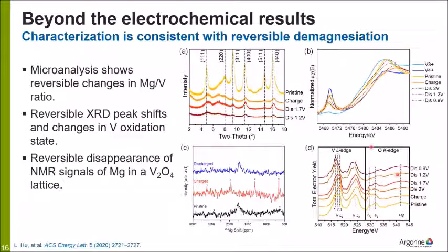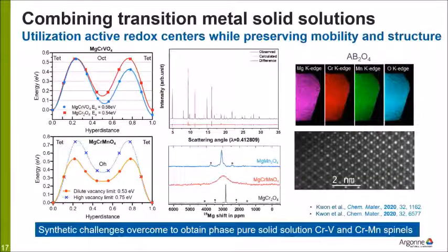And finally, we even looked at surface-specific versus bulk-specific emission spectroscopy results. And once again, you can see, even at the surface, this sort of oxidation shifting of the vanadium that's consistent with the rest of the data, in that the magnesium indeed is reversibly moving in and out of the structure. So we now have the two end members. We have the manganese, we have the vanadium, and then we began to look at